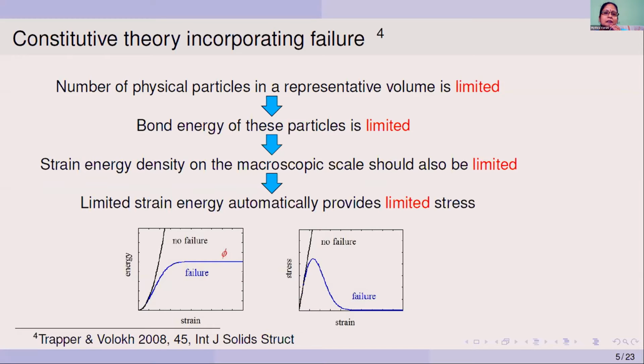So we formulate an expression for the strain energy density function which includes energy limiters. This energy limiter is the average bond energy or the failure energy, which is denoted by phi as shown in this figure. These limiters automatically constrain the permissible stresses and induce strain softening as shown in this stress strain curve.